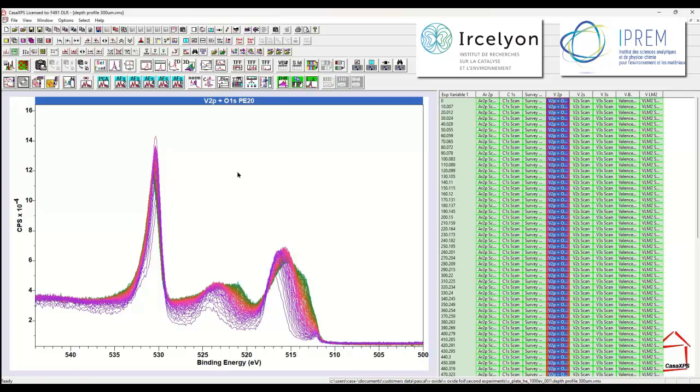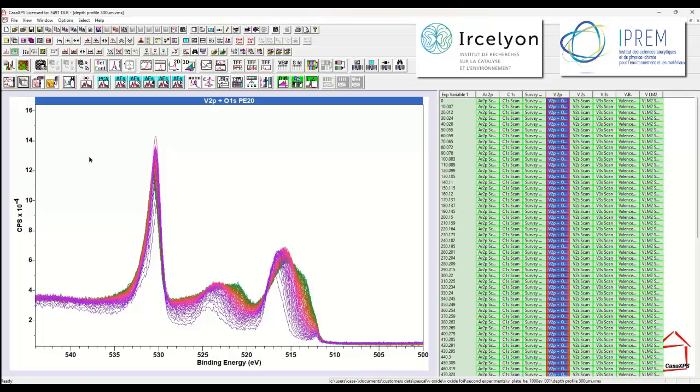In fact, we will find multiple abstract factors, and the multiple abstract factors will give us an indication of how many shapes are within these data. It won't tell us precisely how we would go about fitting these data, but it will tell us how many different shapes that we need to identify before we can use those shapes to fit the data, and hopefully interpret the data with some physical meaning.